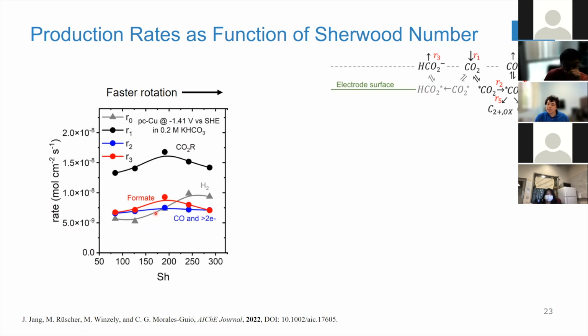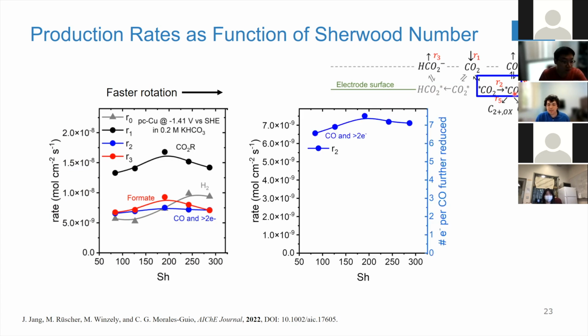And if you look at this step here, R2, that is the transformation of CO2 to CO, and then CO to further reduced products. But R2 is just this first step. We actually see that it's constant as we change the mass transport. So as we change the mass transport, the transformation of CO2 to CO is not affected, even though we're bringing more CO2 to the surface of the electrode. This plot takes that CO rate, R2, and breaks it down into the different pathways that you have once you make CO.